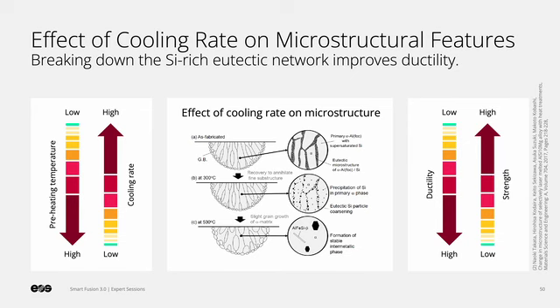Studies have shown that the preheating temperature of the building platform, which results in a change in cooling rate, has a significant impact on the morphology of the silicon network in this material. Here in this slide, we see that an increase in preheating temperature of the building platform reduces cooling rates, and this will cause degradation in the silicon network. The silicon-rich phase starts to dissolve and the network structure changes into coarse large particles. As I explained previously, this phase is a non-deformable hard phase. Dissolution of this phase and change in morphology increase ductility of the part and reduce hardness and strength.